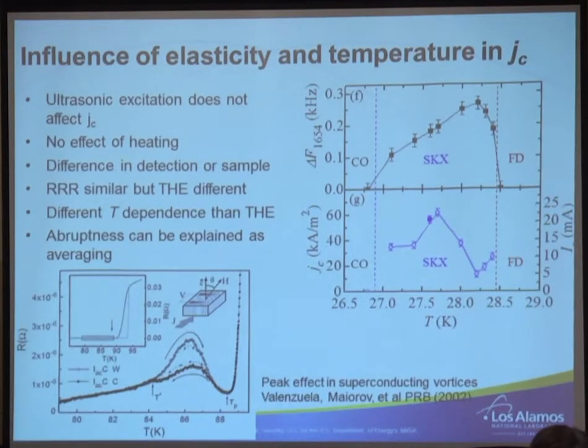So what we can do now is compare the stiffening and the critical current as a function of temperature. The first thing we see is that this is different to what you expect if you have a critical current that only depends on the elasticity. If a critical current only depends on elasticity, then basically JC should be an inverse of this. Here it should go down and then it should go up all the way. And we see that happens in this region. This goes down, so inverse of this, and then it starts going up. So this critical current we are measuring does not depend solely on the elasticity.